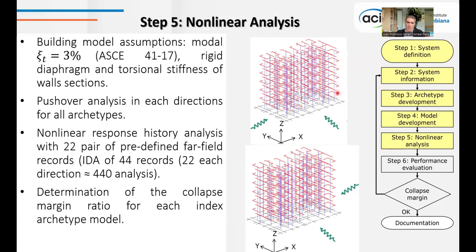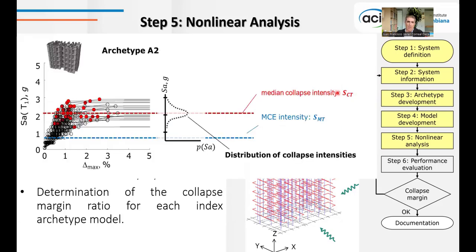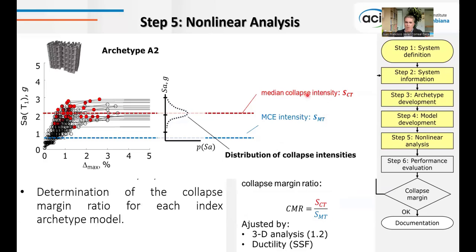After that, we're ready to determine the collapse margin ratio for each archetype model. This is just a picture of how we did that. The dots are the failures for each earthquake that we found, and then we have a distribution of the collapse intensities. Then we take the median of the collapse intensities, and we calculate the MCE intensities that come from the design spectrum. If you take the median collapse intensity divided by the MCE intensity, it gives you the collapse margin ratio based on the methodology. Then it is possible to do some adjustment if you use a 3D analysis, which was our case, and also an adjustment of the collapse margin ratio for the ductility.